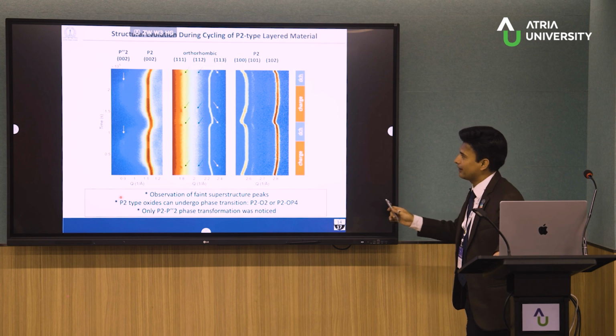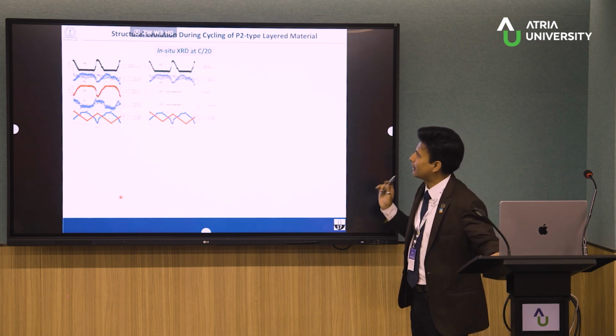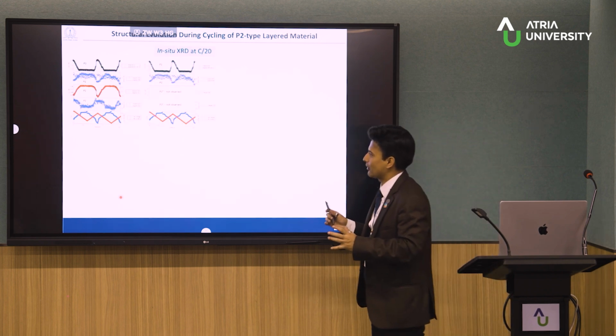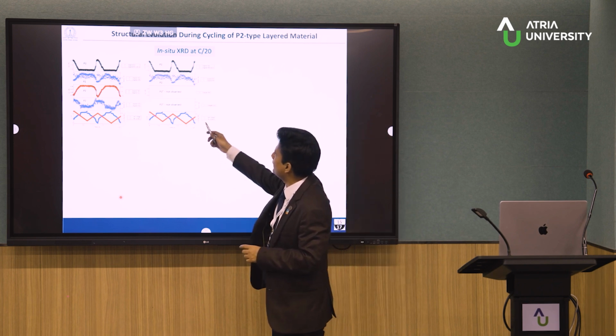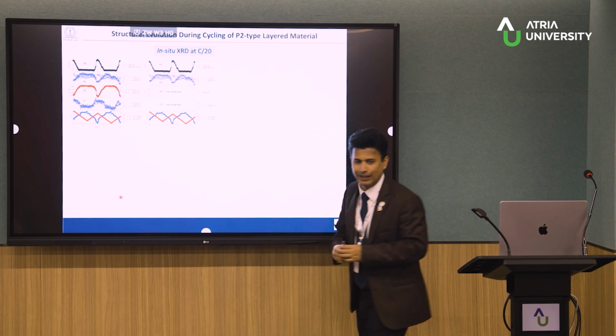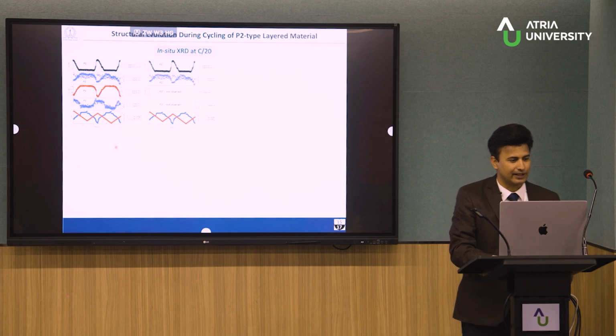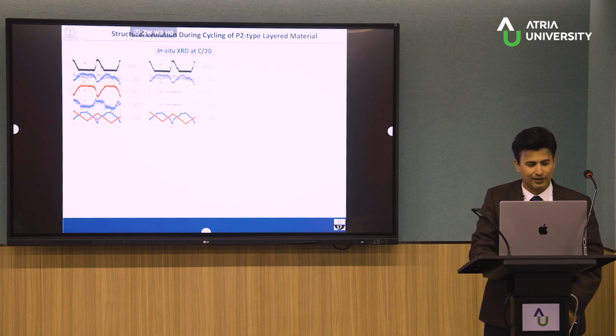Now we did this kind of in situ XRD study for different rates. I want to show you some examples. This is the in situ XRD study done at C/20, the typical C/20 rate. During the charge and discharge, you can see the sodium content decreasing and increasing. That is very well known. During the process, you can see how the P2 phase is decreasing, then again increasing. And here also the P2 phase, how it increases and decreases.